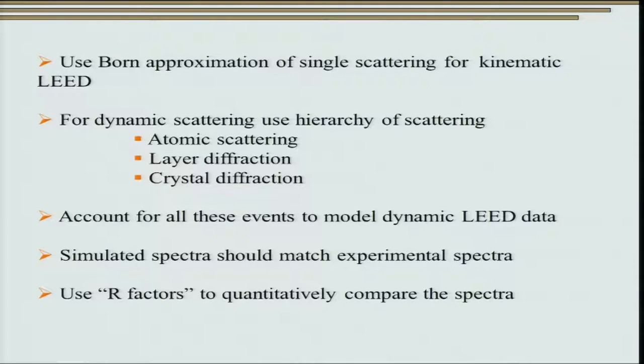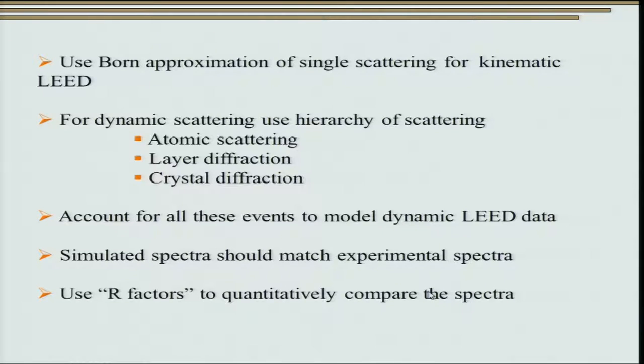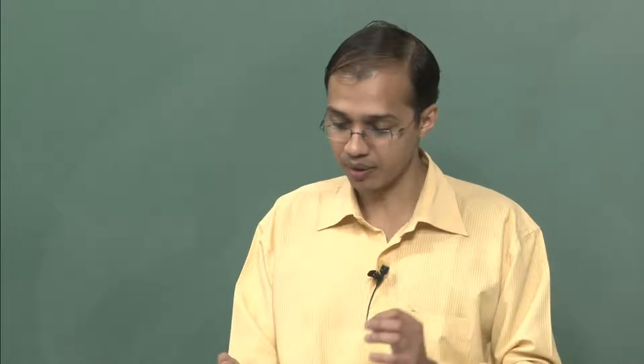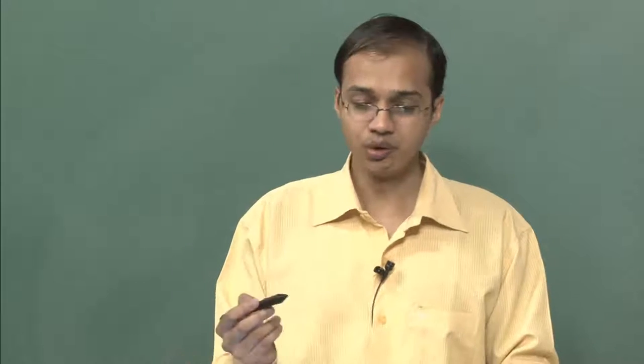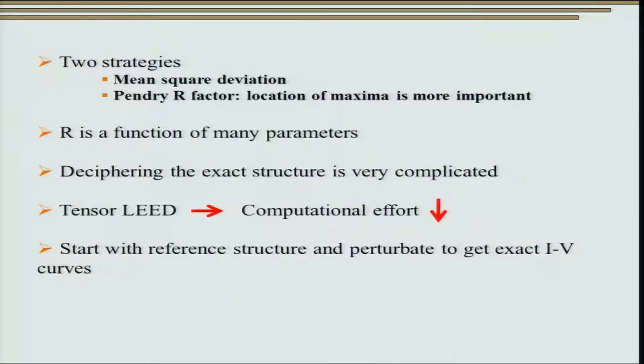When we actually get the LEED data, we account for all these events to model the data. Our job is to obtain a simulated spectrum that shows a good match with the experimental spectrum. It is very difficult to compare two spectra visually, so we use R factors to quantitatively compare them. Two strategies have been used: mean square deviation and the Pendry R factor. In mean square deviation, we minimize the deviation between simulated and experimental pattern. In the Pendry R factor approach, the location of maxima is more important.